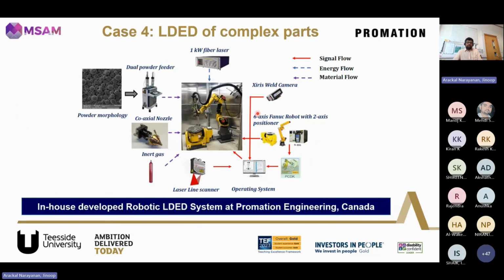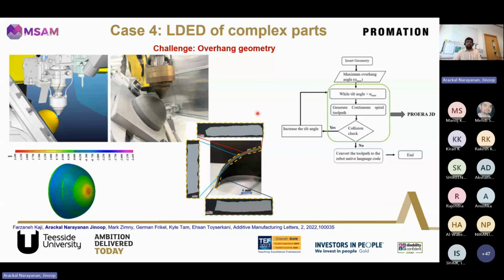So the next one is more the work that we did at University of Waterloo. This is a 1 kilowatt fiber laser, which is used for the DED process using a powder as a feedstock. So we did works on overhang geometry like dome structures. We did the toolpath planning for this, and my involvement was more into the process and characterization part of these structures, while my colleague Farzaneh Kaji, she was the lead author in this particular paper. She was involved in developing the toolpath and developing the algorithms for this. So we were working on developing these dome structures, processing of this, and characterizing and qualifying them for different applications.